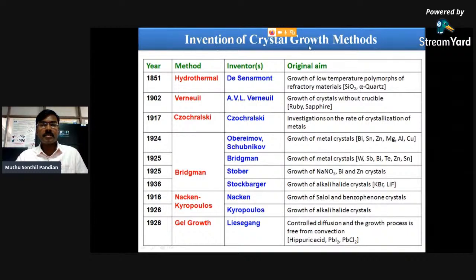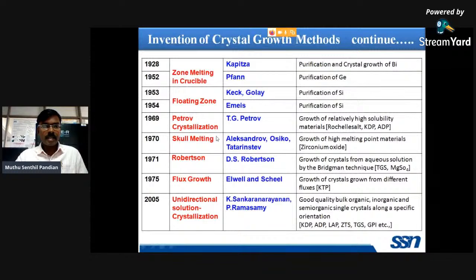These are some of the different crystal growth techniques available, and for practical device applications, most crystal growth people use solution and melt grown crystals. In 1851, the hydrothermal method was used for growth of quartz crystals and SiO2 material, and in 1902 the Verneuil method was used to grow crystals without a crucible, like ruby and sapphire. Similarly, there are a lot of crystal growth methods available to grow good quality single crystals for practical device applications. In the present lecture, I am mainly concentrating only on the conventional slow evaporation method and the unidirectional Sankaranarayanan-Ramasamy method. The inventors are Professor K. Sankaranarayanan from Alagappa University, and Professor P. Ramasamy, who was my PhD supervisor, from Anna University.